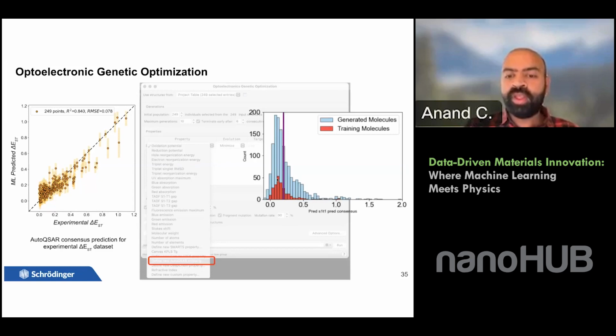And so the red histogram here shows the distribution of the optoelectronic properties, or distribution of the delta EST values, of the training set. And the blue line shows the distribution of the delta EST values of the generated molecules. So we can see here the genetic optimization is quite effective in generating compounds of delta EST value closer to zero.